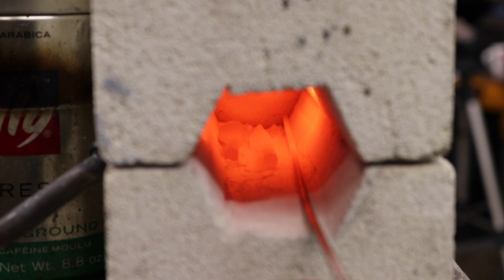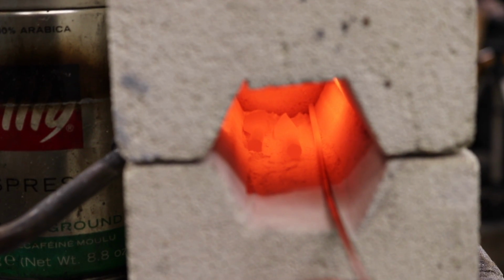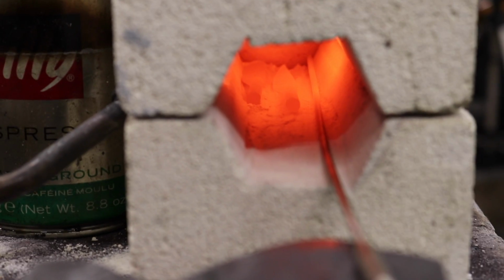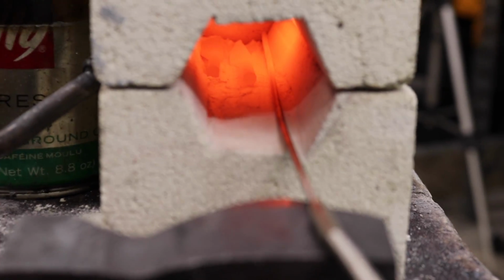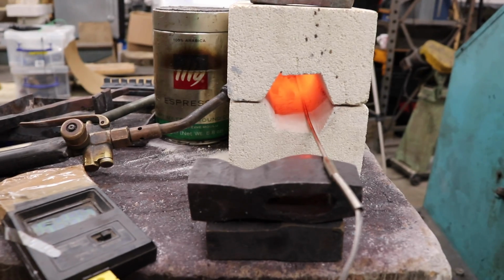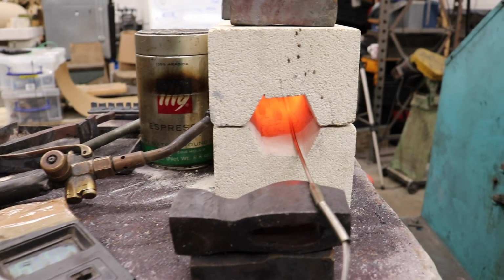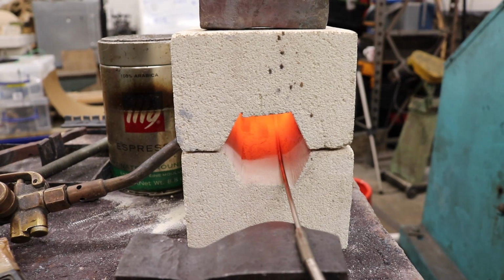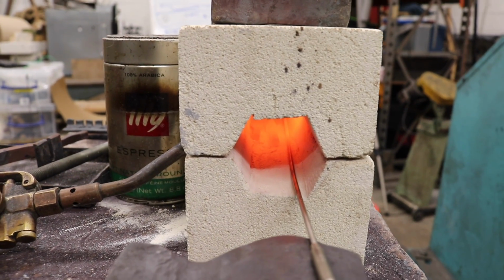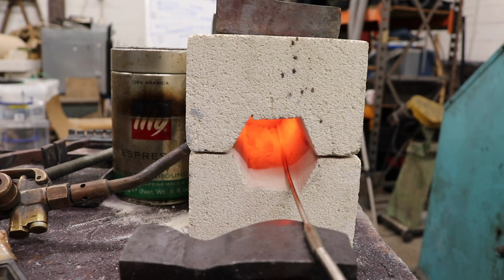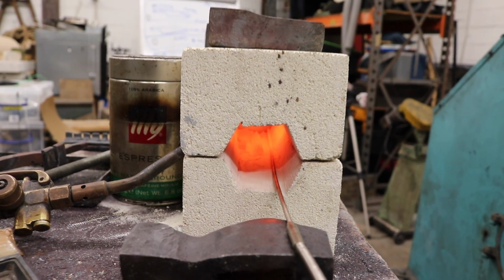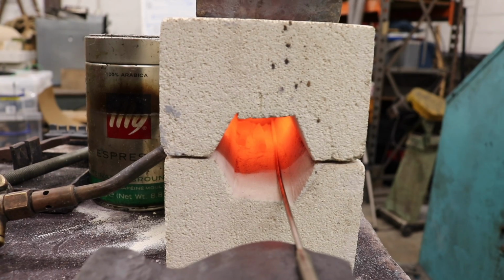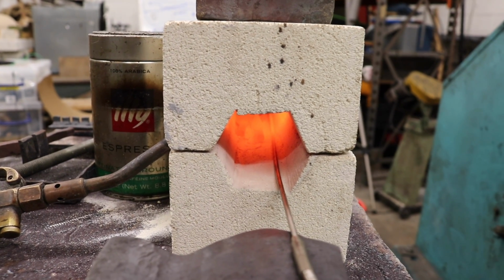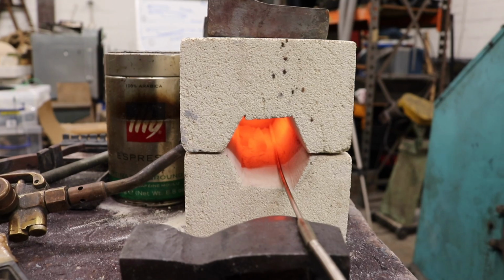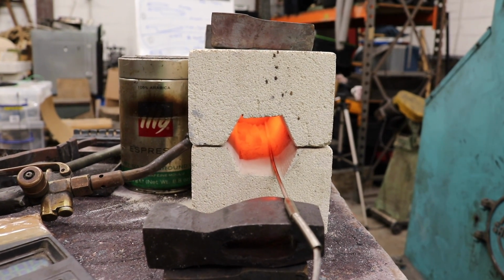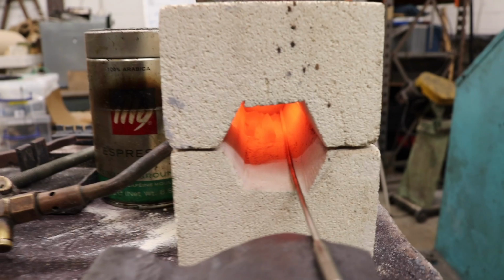Okay, so one thing to be aware of with running a furnace like this is that the thermocouple just tells you how hot the thermocouple is, and that's not necessarily the temperature of the blade steel. So you always need to check that when you're at your right temperature range. The trouble with a digital reading is that if you've got your eyes set on 840, you'll want it bang on 840, whereas the reality is anywhere between 820 and 850 is probably fine for normalising cycles. It's not that critical. What you're looking for is that the thermocouple is in the temperature range you want, and the blades look to be the same colour, which is the same temperature as the thermocouple.